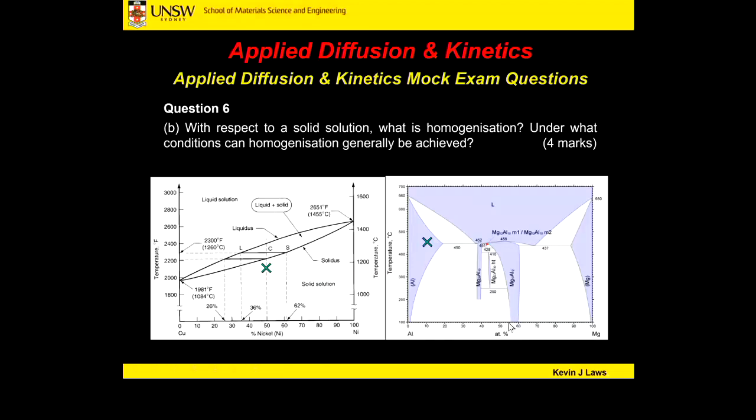Here's our example of the aluminium magnesium system. To homogenize this, depending on the composition of our alloy, we have to raise our temperature out of usually a dual phase field, between this intermetallic and the solid solution, to a point where we're within the solvus bounds, there's our solvus bounds, and within the single phase field. We also know at this temperature that our solubility is going to be highest in this axis here.